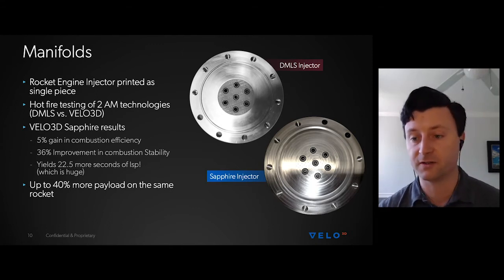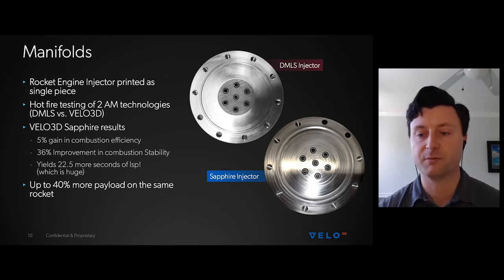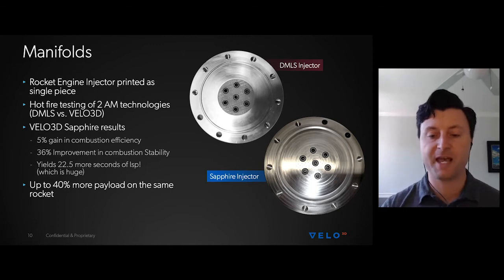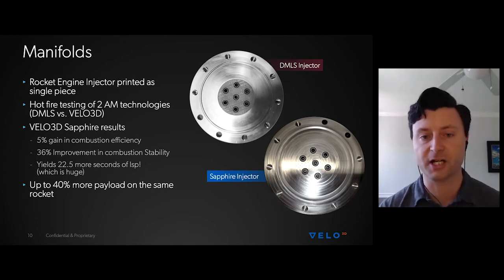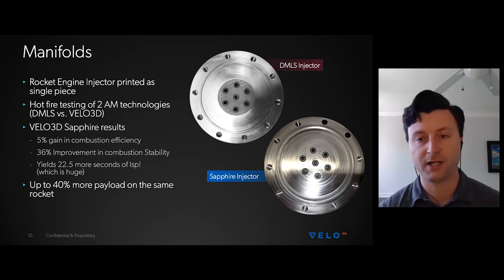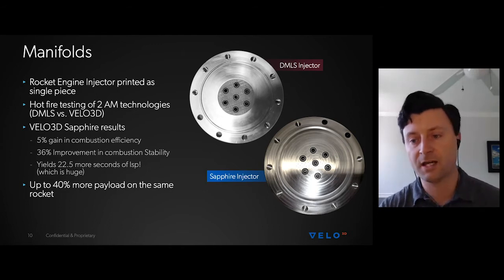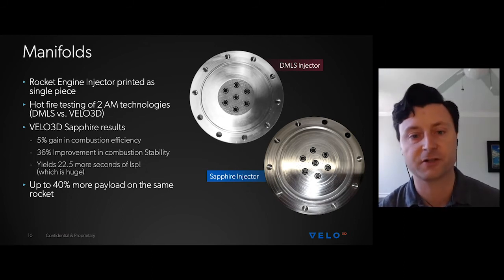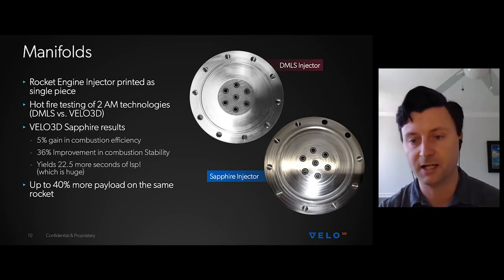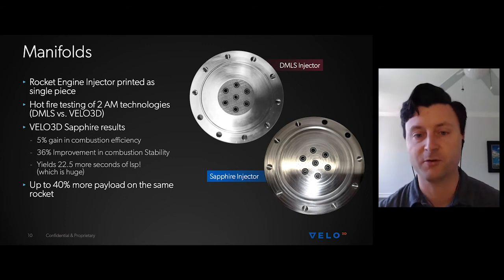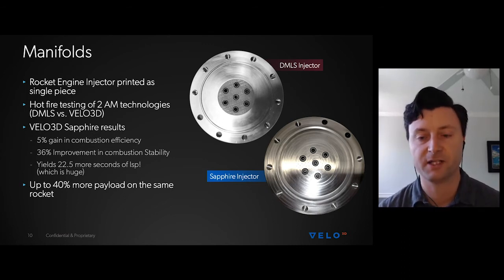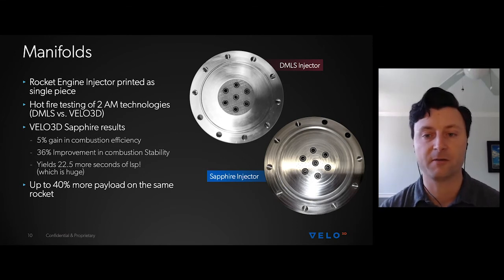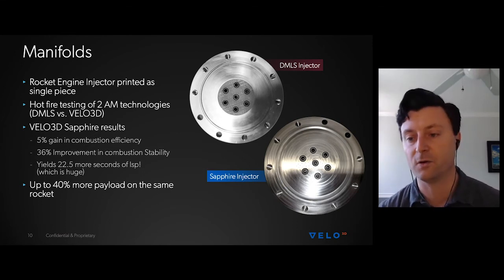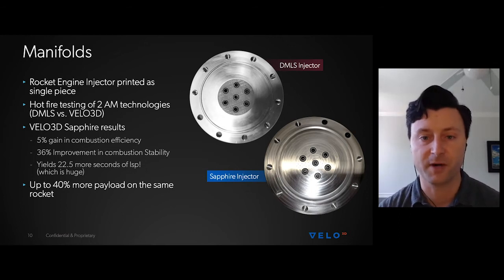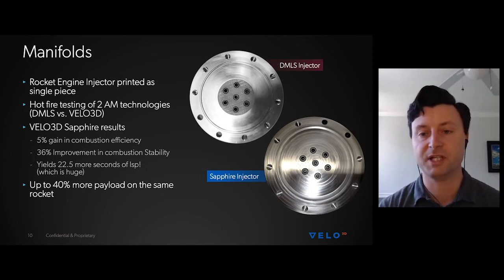So as far as I know, this is one of the only monolithic injectors that's been produced and hot fire tested. And that's really important because what they've done is taken all of the manifolding that would normally go on the backside of an injector and integrate it so that it's all printed in a single piece. So while you're just seeing the injector face in these pictures, what's going on behind it, and which is export controlled, so it can't really be shown in a presentation, is a lot of really amazing design work around manifolding to get the fuel and oxidizer to the injector face in the right manner. So this was printed as a single piece.